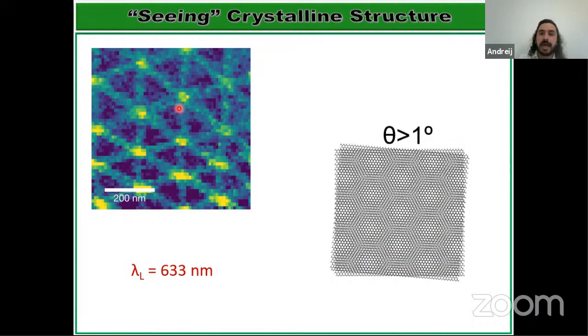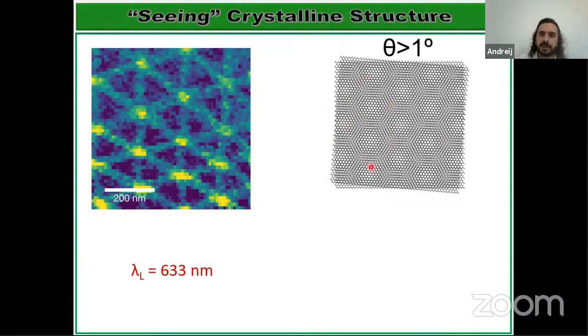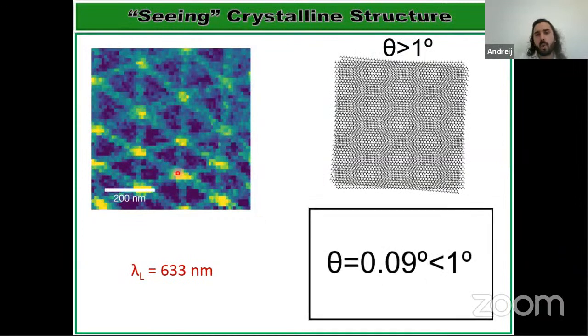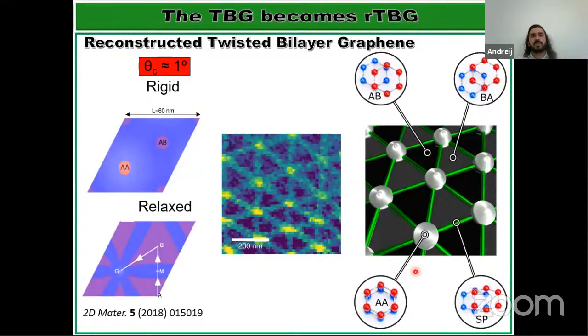And there is another question. I showed you before that the Moiré pattern is something like this. So we have some hexagons here, while the image that we measure has some triangles. So something is confusing here. You may say that the nanoscope is measuring wrongly, or that I'm messing up with some information here. Actually, when we have a very small angle, like this one, about 0.09 degrees, which is smaller than 1 degree, a new material shows up. So the TBG now becomes rTBG, which is reconstructed twisted bilayer graphene.